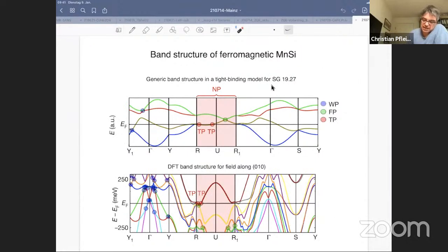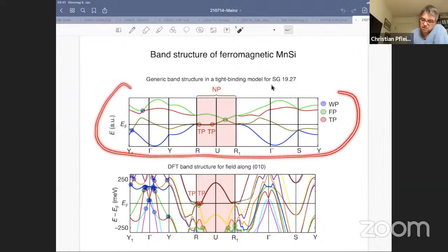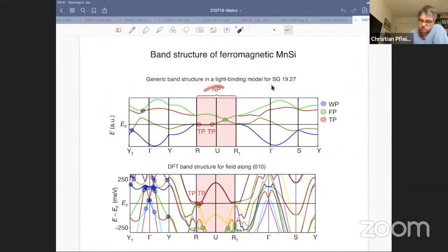Here's a picture of the calculated ferromagnetic band structure in MnSi, and you get a very similar situation to the cobalt silicon. However, you have more bands. And then if you do this whole thing, basically spin split, taking into account spin-orbit coupling, this is just for a generic model. You can see the nodal plane and these crossing points here. You see that there are more crossings, but the story essentially stays the same. So you have these Weyl points, fourfold crossings, and then you have these topological protectorates wherever the nodal plane or the Fermi surface hits the nodal plane.